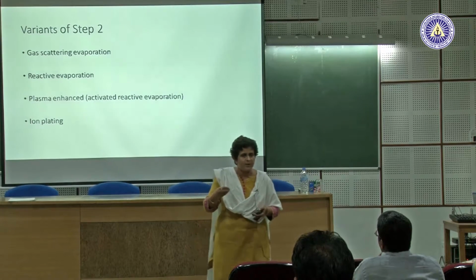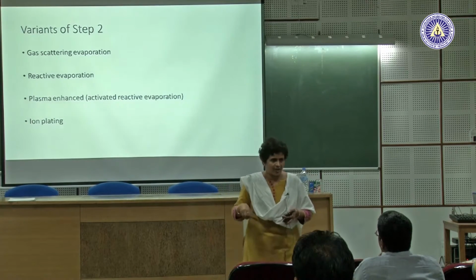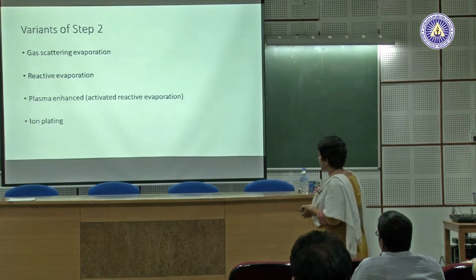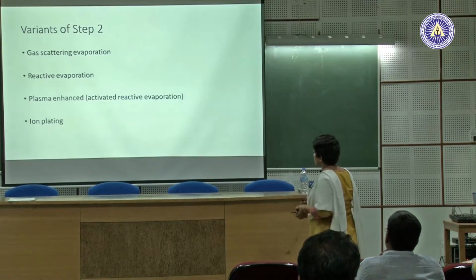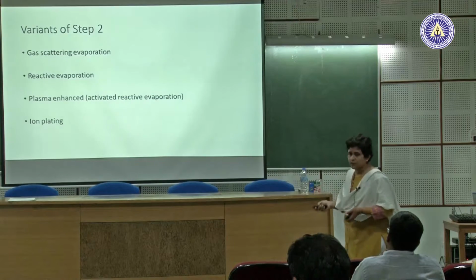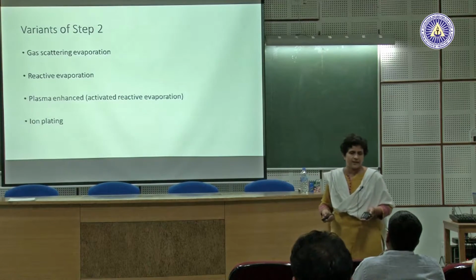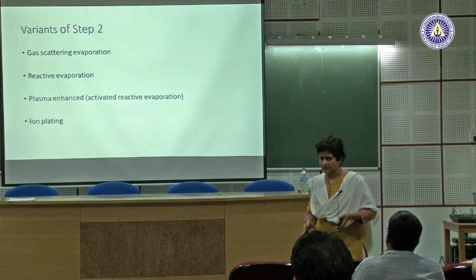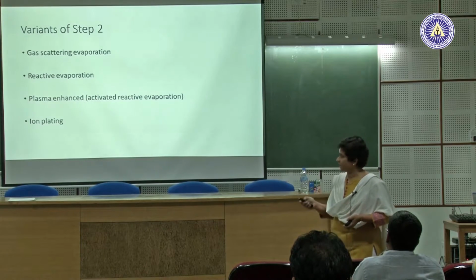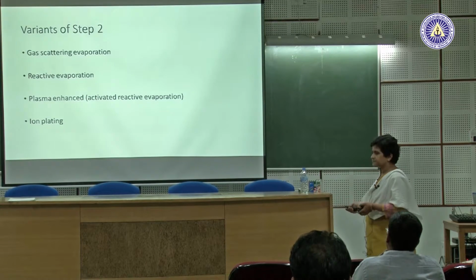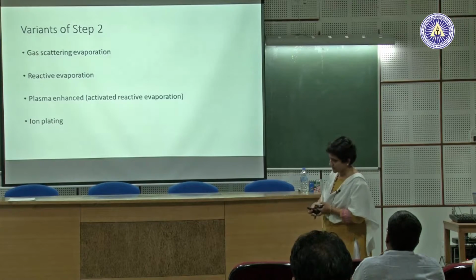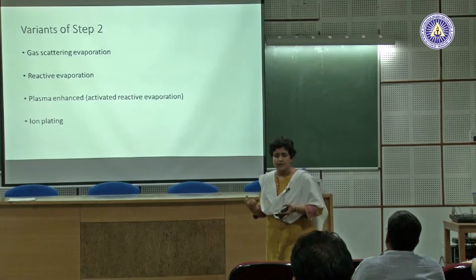So, sometimes people used to do intentional scattering, so that there is more uniformity in the deposition. Reactive evaporation: I am evaporating silicon, I put in oxygen, I will get silicon oxide in the gas phase. Plasma enhanced, and this gets into, again, materials issues.